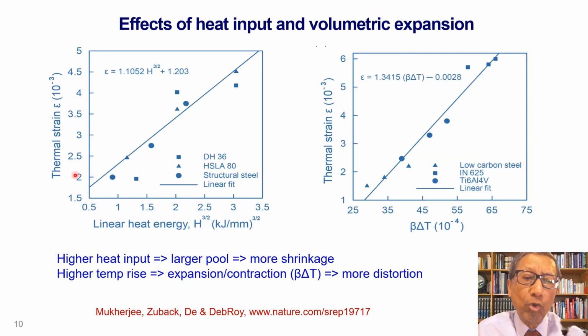This plot shows that the strain is linearly proportional to heat input per unit length raised to the power 3 by 2 based on independent experimental data. Similarly, when we plot beta delta T and thermal strain, the thermal strain is also linearly related to beta delta T, as we would have expected based on the model that we developed.